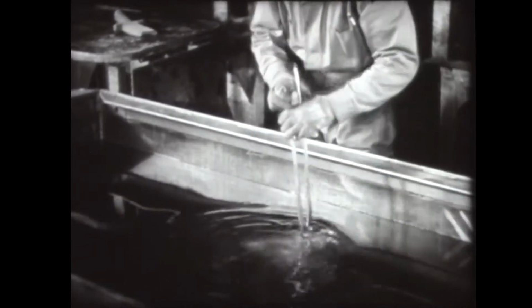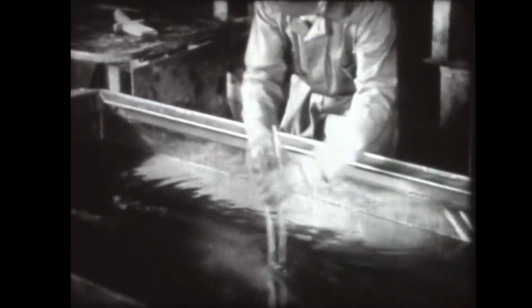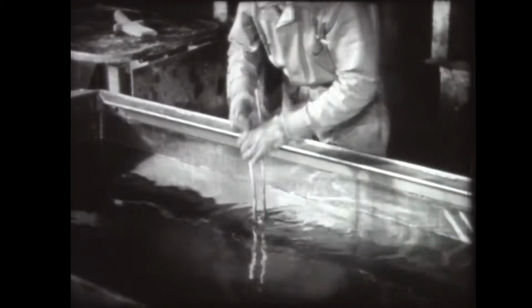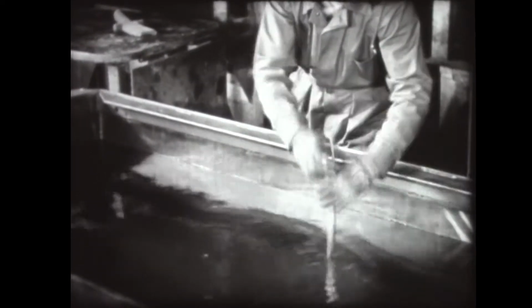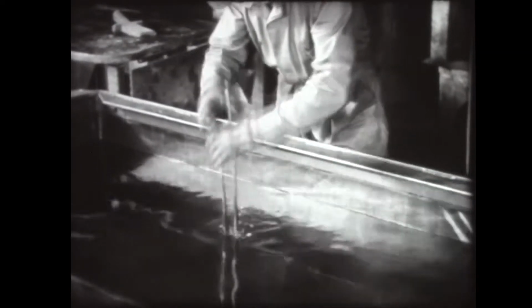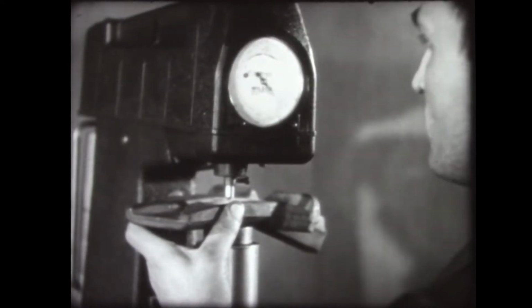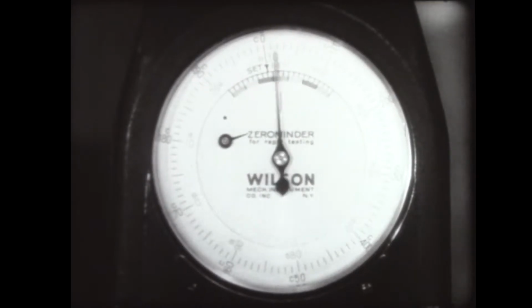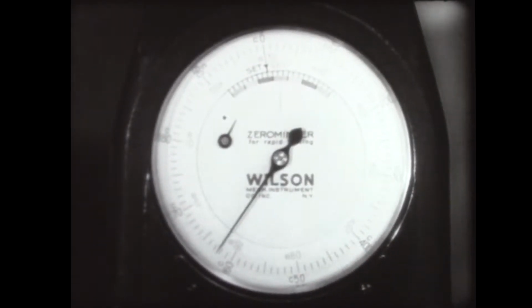They are quenched, cooled rapidly in water. Heating and quenching together produce desired changes in the properties of the steel. After quenching, the heat treater again makes a Rockwell hardness test. The test reveals that the part has been hardened to about Rockwell C 62, 7 above the hardness called for. It has purposely been hardened to a point above specifications. Tempering, a toughening process, will bring the steel down to the exact required hardness.